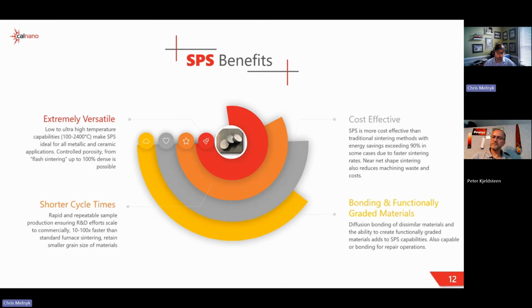There are different advantages, high voltage versions now that are up in the hundreds of volts, versus all of our systems, which typically operate between about 5 and 10 volts. That is a typical voltage. So amps come easy when you're at low DC voltages. But how do you make it high voltage? Do you change the die material to less conductive?